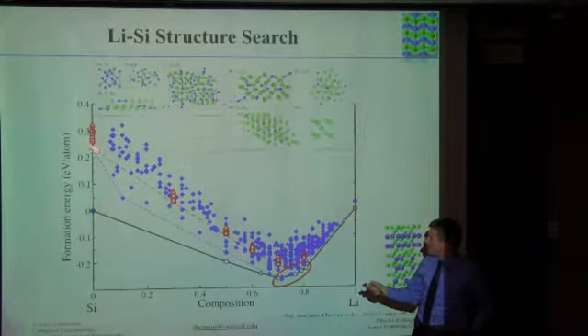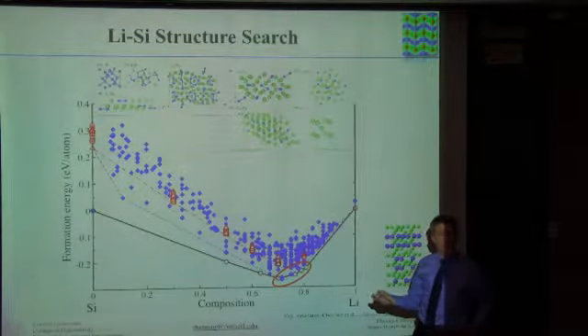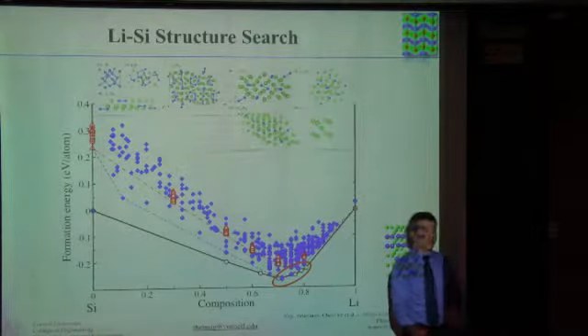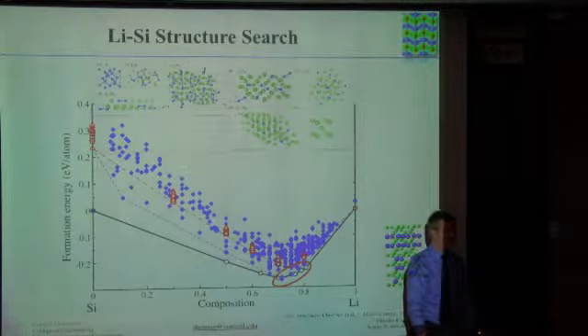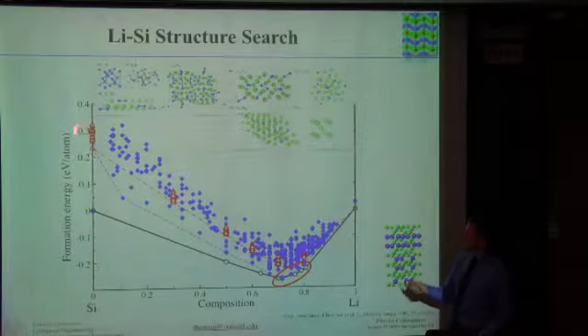The reason we didn't is we started with amorphous silicon here. The red point is the amorphous structures we generated. We take a chunk of lithium silicon, we heat it up, we quench it down, we heat it up a second time to see if it changes, and here's the data points we find there for what the energy of amorphous lithium silicon is. And we get this curve.